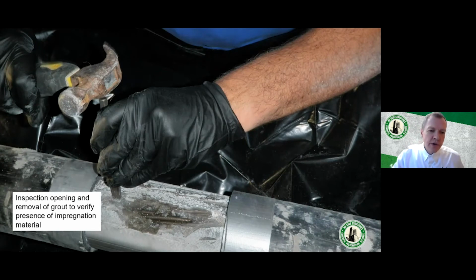That project I just showed you was actually the first full-scale field project that we did for Florida DOT, and they hired an outside consultant to basically do some quality control inspection. They made some openings in the ducts that you see here, actually 24 of them in the first tendons that we did, and they removed the duct, they carefully removed the grout, and they wanted to verify that the impregnation material was in and around the strands, which you can see in this photograph.